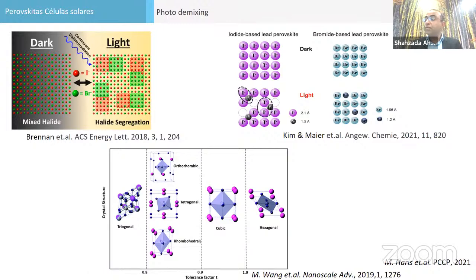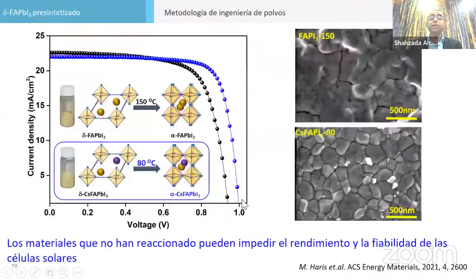There's another factor we call the tolerance factor, for increasing this stability. We found that for tetragonal, trigonal, cubic perovskites, if the tolerance factor is close to 1, then higher stability can be achieved. So methyl ammonium is not good, but formamidinium has a tolerance factor close to 1. That's why it's more stable here. I will show you some examples of formamidinium, delta FAPbI3.